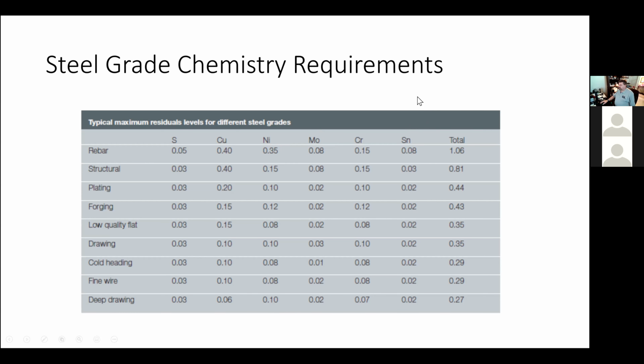And if we removed all of the iron and oxidized it back to iron oxide, we wouldn't be very good steel makers. So what we typically have to do, if we have to achieve lower levels for certain products, is use some new material that has very, very low residual content in order to make those grades of steel. Chrome is one of these things. It is a residual, but once you get below about a 0.6 carbon content in the steel bath, you can start to oxidize chrome out. And obviously that's very important when you're making things like stainless steel, where you want to keep the chrome in there.